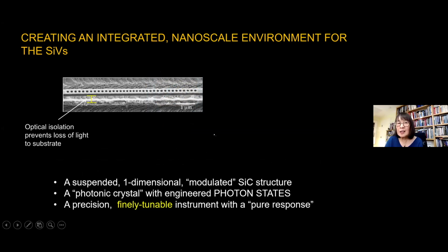What does it actually look like? Well, it actually probably looks much more humble than you might imagine. This is silicon carbide. This is basically a suspended, one-dimensional, modulated structure. You can see that there is this marker here that states 1 micron. There are holes that are punched into the silicon carbide, and that's what I mean by modulated. I modulate the structure by a series of periodic holes. These holes, center to center, are about 100 nanometers in distance. It may be difficult to see, but this one-dimensional like structure bridges.